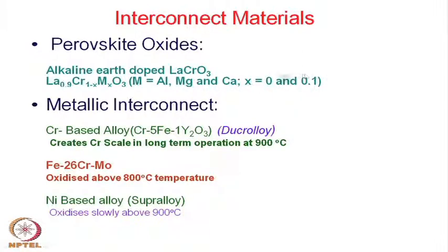It is only about 0.1 mole percent. Okay. So, this is how the material is prepared. However, this is not the current level of thinking. Currently lanthanum chromite is not being used more because one of the reasons why lanthanum chromite is not being used in the later versions or in the current fabrications is the chromium diffusion.